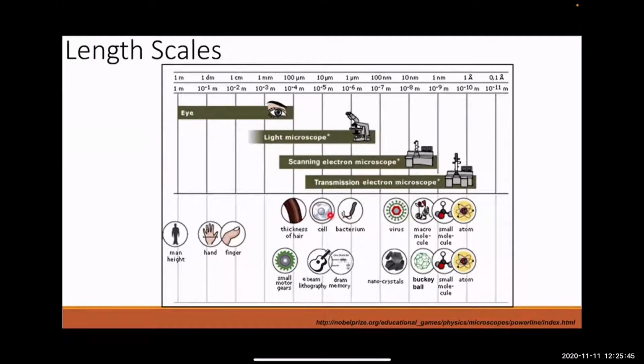But if you wanted to see structure inside the cell or features on the bacteria at a smaller length scale, the light microscopy is going to come to a hard limit. And that's where EM comes in, both in the form of SEM or TEM. SEM is typically, it can go down to about 1 nanometer. There are specialized cases where an SEM has shown full atomic resolution, but that's a very specialized case. Typically, 1 nanometer nowadays is kind of where it caps off.